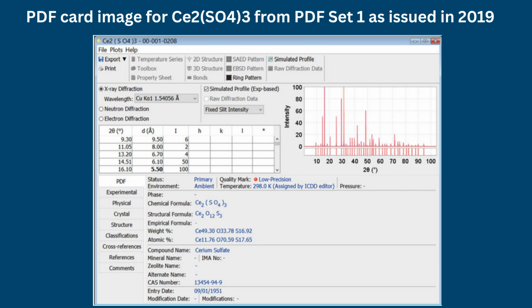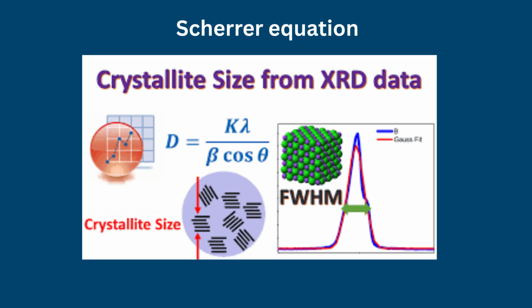Each crystalline material possesses a unique diffraction signature determined by its atomic arrangement. Peak positions provide lattice spacing information, whereas peak intensities reflect atomic distribution and preferred orientation. Peak broadening is often analyzed using the Scherrer equation to estimate crystallite size in nanomaterials. Additionally, lattice strain and defect concentrations can be quantified from variations in peak width and asymmetry.